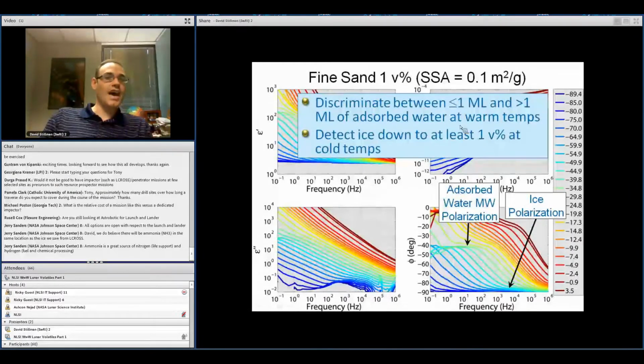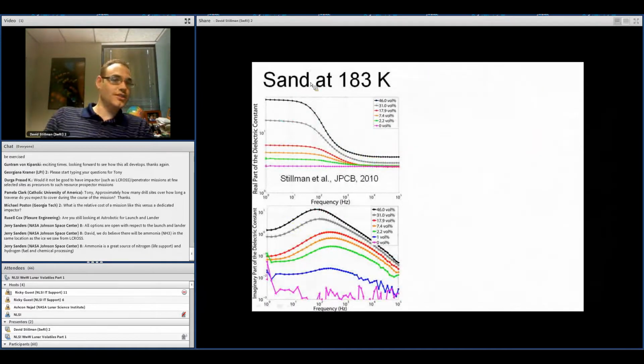So we can not only detect ice at one volume percent, but we can also look at adsorbed water. We can see if there's at least one monolayer, and then if there's more than one monolayer by these different polarization mechanisms. So here's an example of sand with a bunch of different volume percents of ice in it. And here we're going to talk about quantitatively detecting ice in the subsurface. So we have different amounts here, and you can see that this low frequency dielectric constant, permittivity, increases drastically. What you'll also see is that the relaxation frequency, again where the maximum is in the imaginary part, actually shifts to a higher frequency. So this is actually a good thing for us.